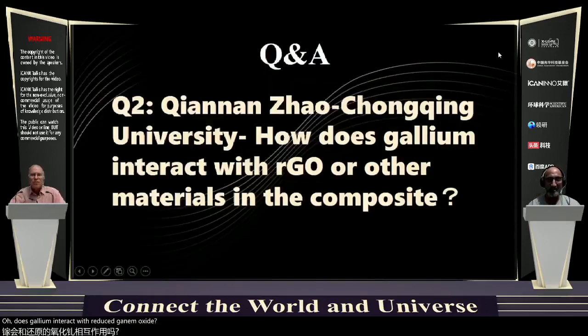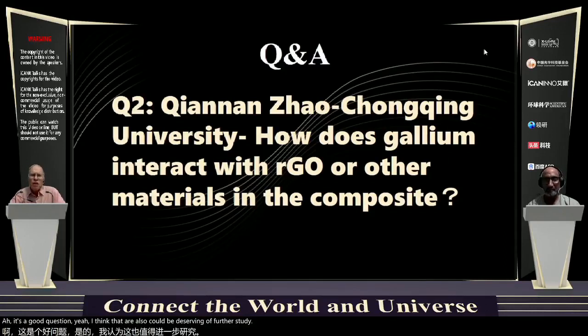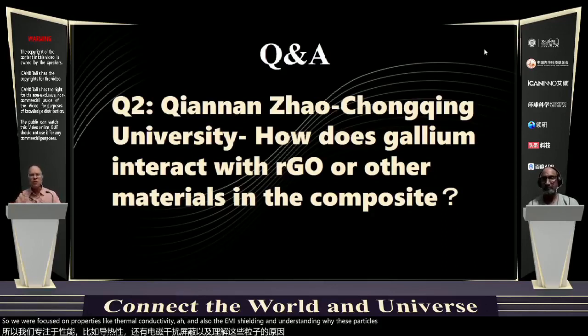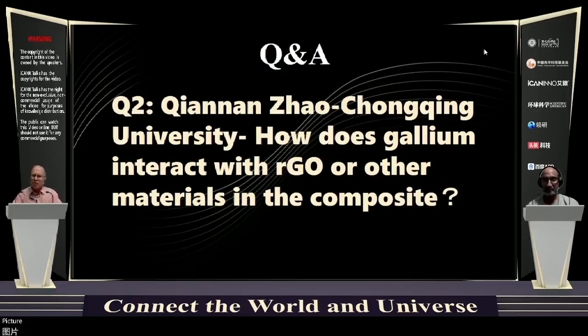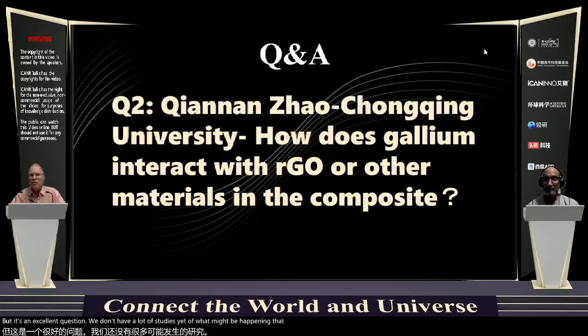How does gallium interact with rGO or other materials in the composite? That's a good question. I think that also could be deserving of further study. We haven't seen any evidence of strong chemistry, for example, between the reduced graphene oxide or diamond or graphite particles, but it's not something we've investigated deeply. We were focused on properties like thermal conductivity and also the EMI shielding and understanding why these particles were mixing in terms of this gallium oxide skin picture. Gallium oxide is a very stable material. It's an ionic solid, a large band gap material with melting temperature around 2,400 degrees C. So it might be a fairly robust interface between the pristine gallium or pure gallium and these particles. But it's an excellent question. We don't have a lot of studies yet of what might be happening at that interface, particularly over long periods of time.